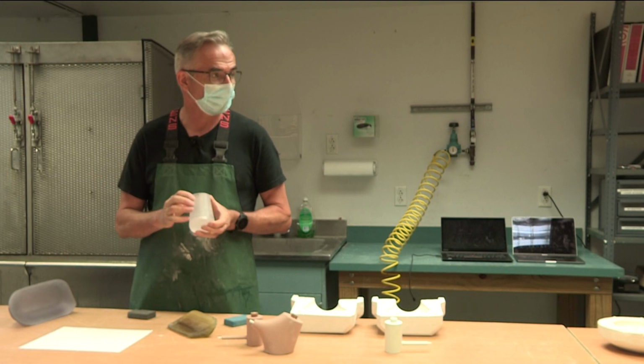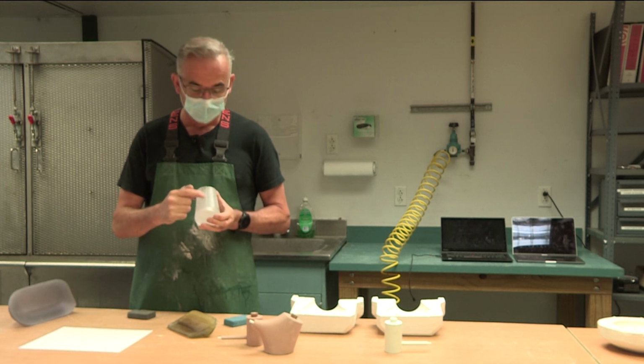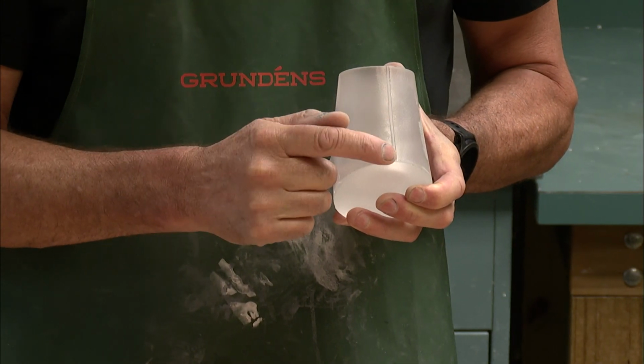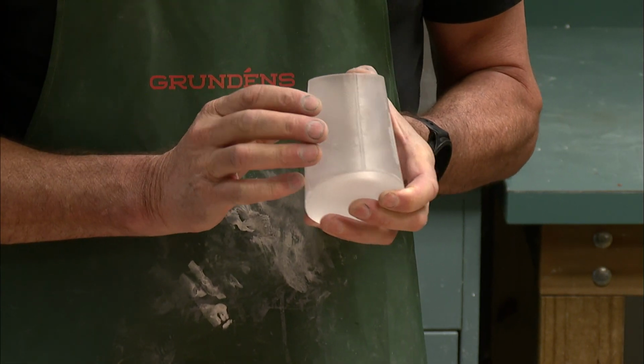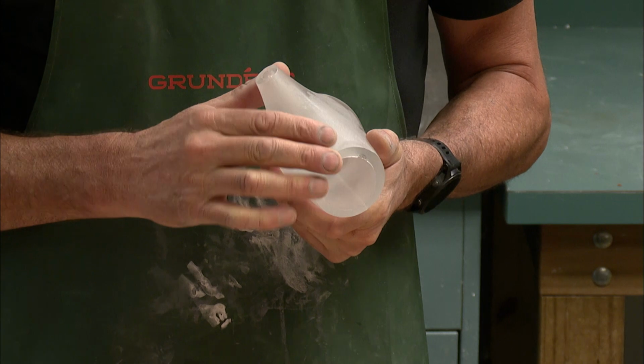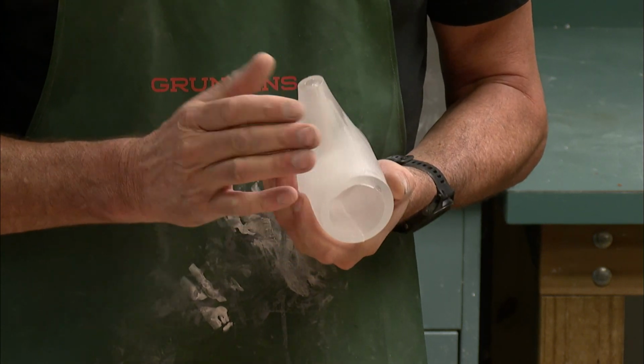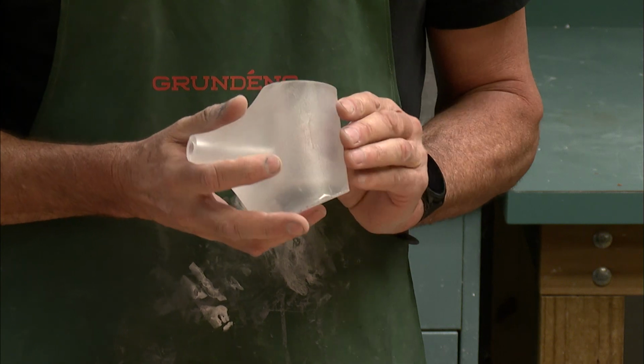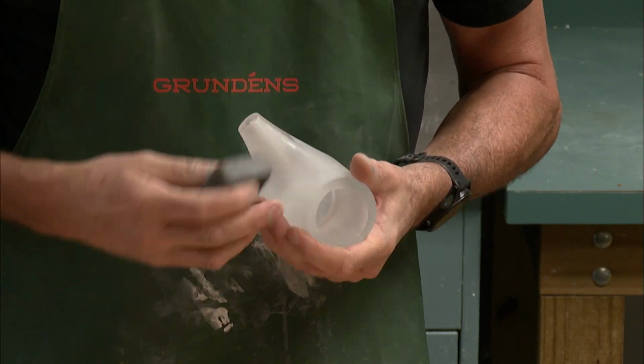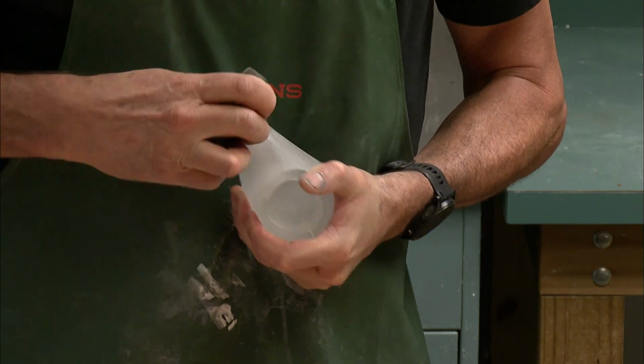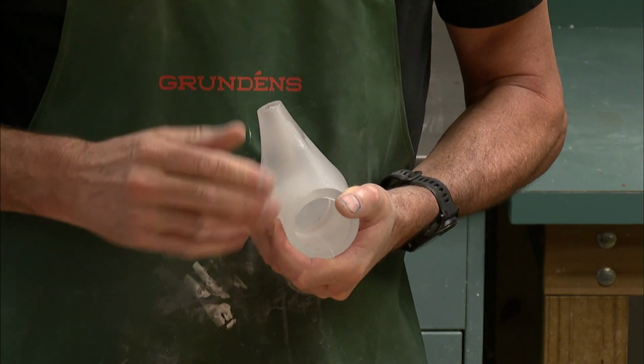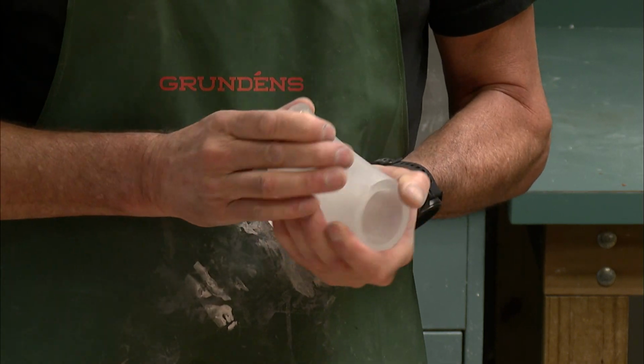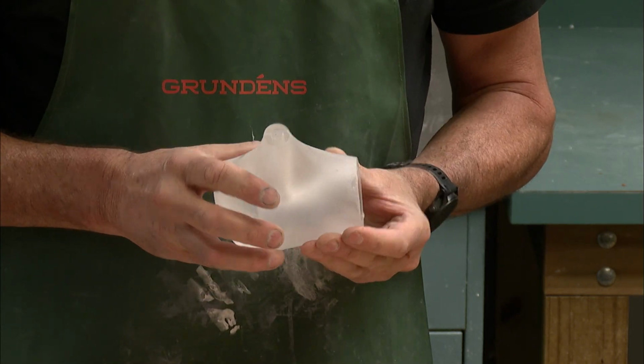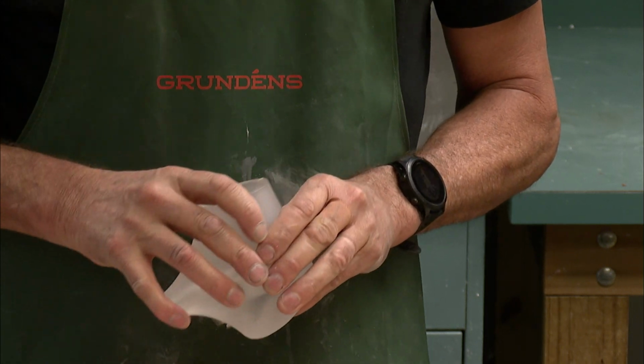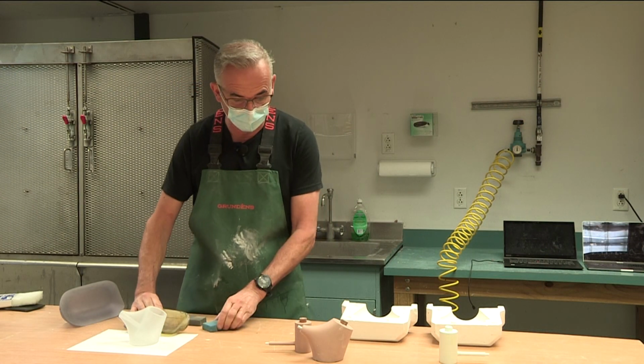But if we just jump back to the regular camera, the technique that we came up with leaves these seams on the surface, and we use an air tool to blend those out. One of the ways we can then unify the surface before this thing gets acid polished, this is cast in Waterford crystal, is just to use these little emery blocks to finish and unify the surface. We use finer ones, and that gets it down to about 1500 before we do that final polish. That project, I might talk to you about that just for a minute.